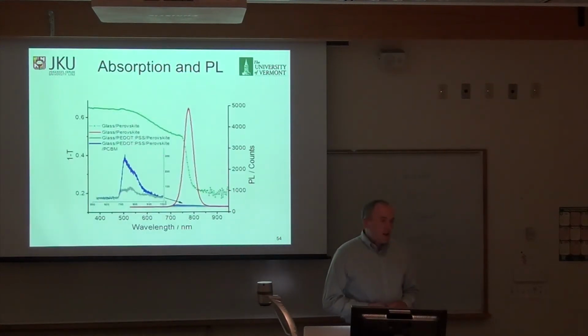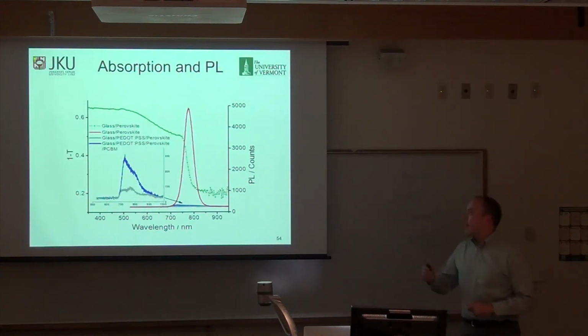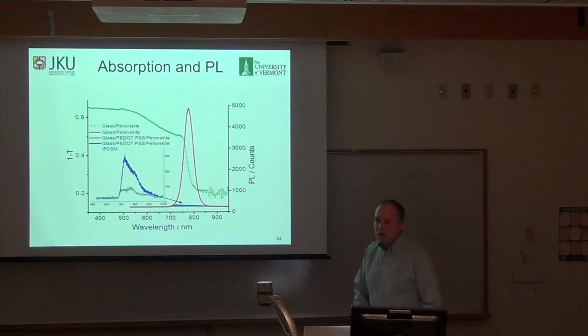We looked at the photoluminescence of these films when they're on different layers. What we noticed is here's the absorption of the perovskite layer. You see it cuts off right at 800, corresponding to the band gap of 1.55 eV. And if you look at the photoluminescence, you have a nice sharp peak right there at 800. But if you put the perovskite layer on top of PEDOT:PSS, boom, the photoluminescence is completely quenched right away.